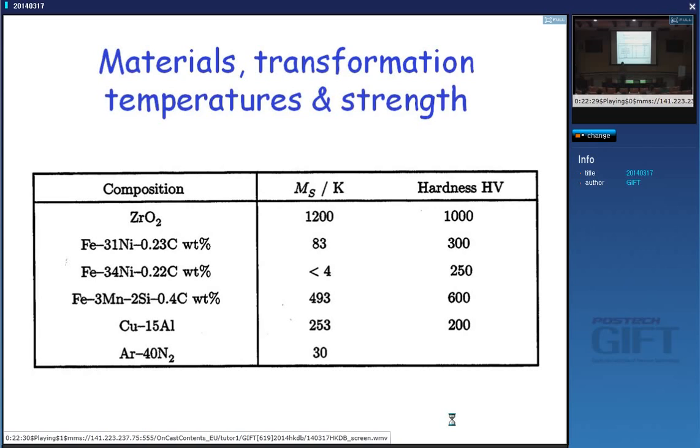It has more space, certainly, but that isn't the main reason why carbon causes a lot of hardening. It's to do with the symmetry of the hole. In FCC, the octahedral hole is symmetrical. So if you get just a hydrostatic strain, that doesn't interact strongly with dislocations, which are about shear. The octahedral hole in the BCC lattice is tetragonal in shape. It's not a regular octahedron. So it causes a tetragonal strain, and that has a huge interaction with dislocations. Dislocations are about shear, not about volume change. So carbon in austenite behaves like an interstitial solute, just causing a uniform expansion. We'll go into this in more detail later on.